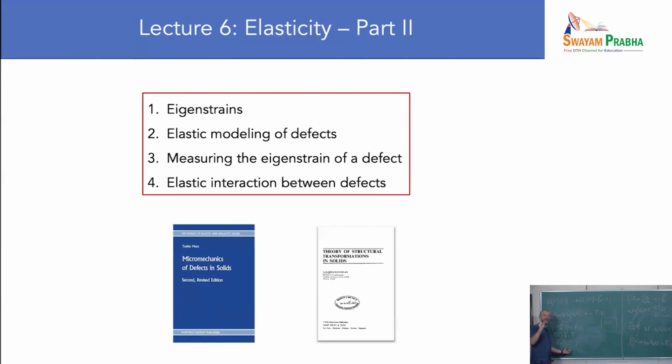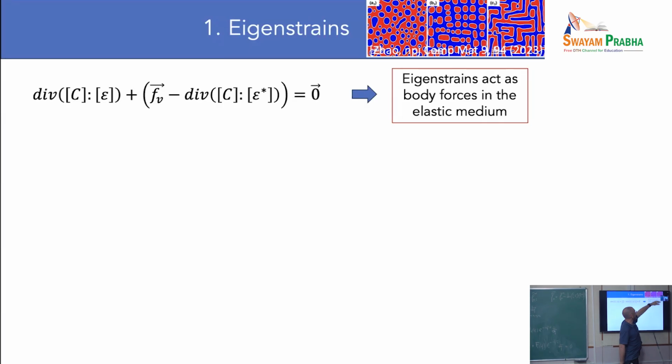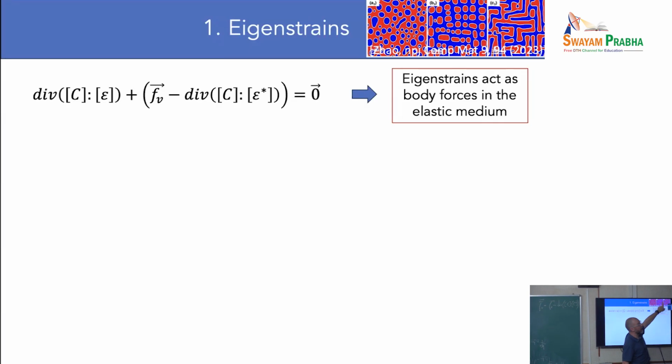I have examples. I'll go back to the slides to make sure that we have all the details, but I'm sure you have all seen this type of phase field simulation where you have precipitations, and because of the elastic interactions between the precipitates and the matrix, you can form anisotropic microstructures. What they are doing here is nothing more than what we have just said.